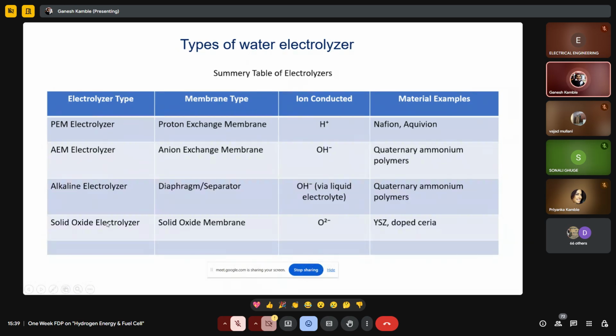In an alkaline electrolyzer, a diaphragm or separator is used, and through this separator the OH- ions migrate. This diaphragm separator is synthesized from quaternary ammonium polymers, as in the anion exchange membrane electrolyzer. In a solid oxide electrolyzer, a solid oxide membrane is used, which migrates O2- ions. Yttria stabilized zirconia material, or yttrium stabilized zirconia material, and doped ceria are used. This type of material is used in solid oxide electrolyzers.